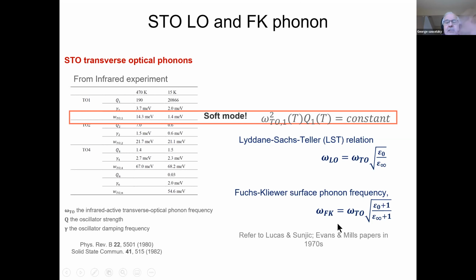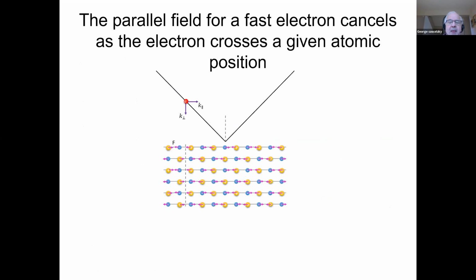And you can work out this theory perfectly, and you get beautifully all of these transverse phonons yielding the Fuchs-Kliewer phonon that you see in electron energy loss spectroscopy. And this is a Q equals 0 mode. It's a longitudinal optical phonon that is polarized perpendicular to the surface.